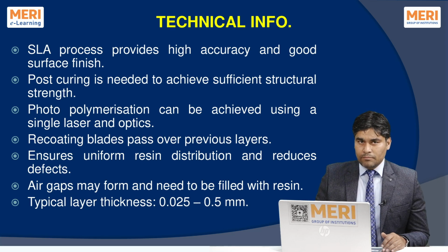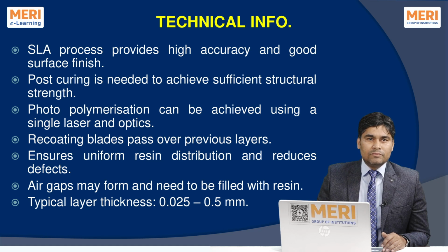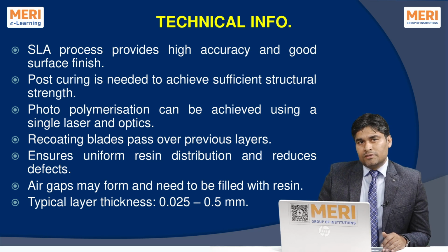After printing, post curing is required to improve the strength and durability of the component. The process uses a single laser along with an optical system to accurately cure the resin surface. During printing, recoating blades help spread resin uniformly, which reduces defects and maintains smooth layer formation. Sometimes small air gaps may form, which are filled with resin during the recoating process.